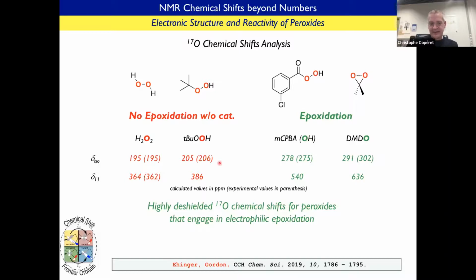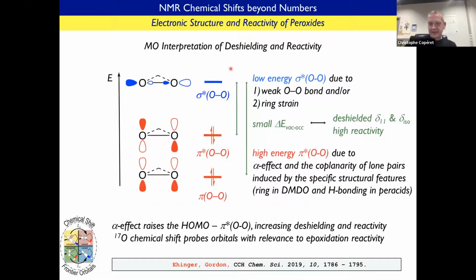It turned out that this seemed to be related to the delta 11 component. So again, the delta 11 component is driving the chemical shift, and it seemed that there must be some information hidden in this NMR chemical shift that explains the difference of reactivity between these two types of peroxide. Again, to make a very long story short, what we have shown is that the origin of this difference in chemical shift is due to the difference of energy between the high-lying pi star and a low-lying sigma star molecular orbital of this peroxo species.